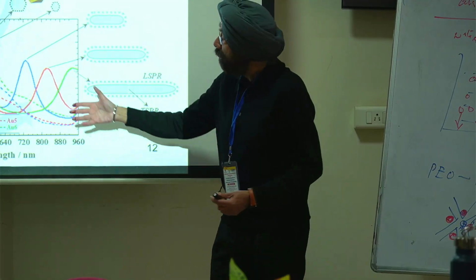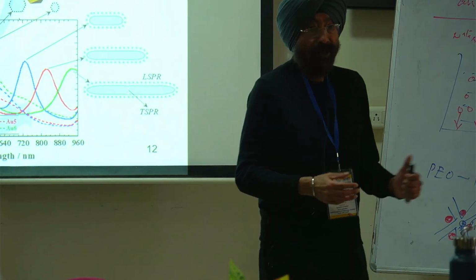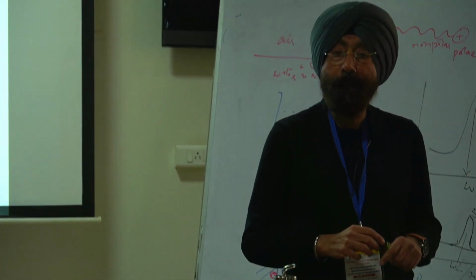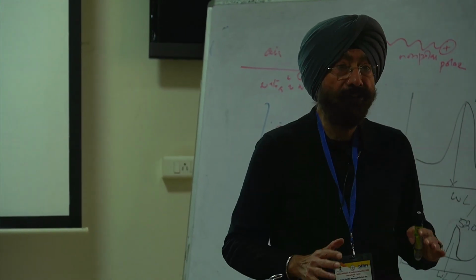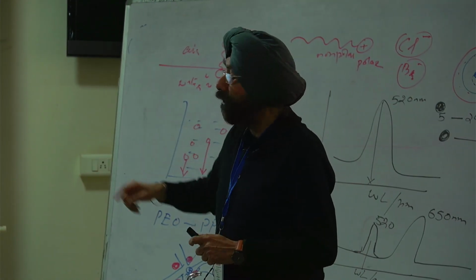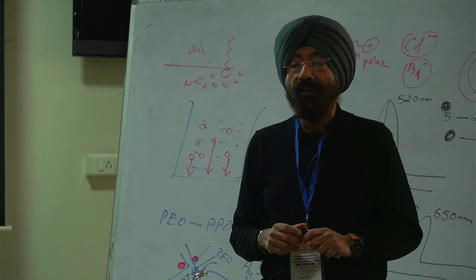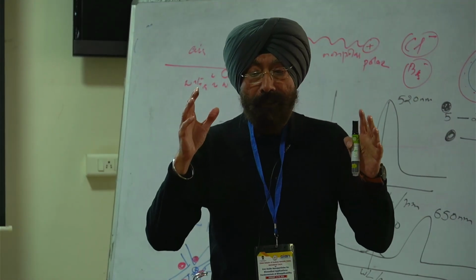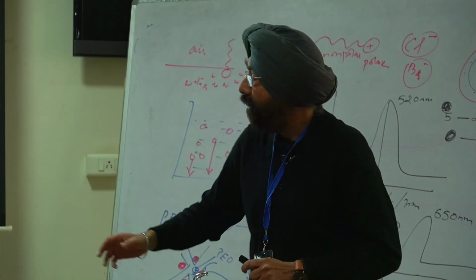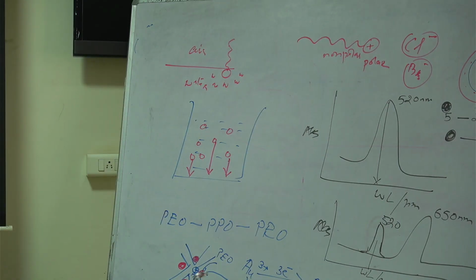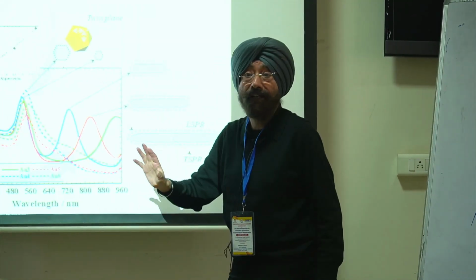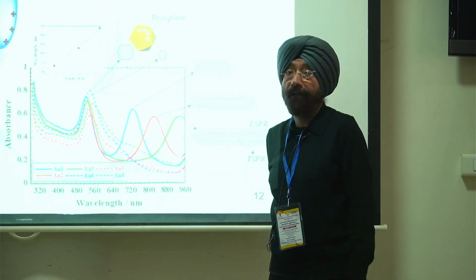So I mean to say, this is the simple way you can test what kind of nanoparticles you have synthesized and what the tentative shape should be. If it is only one kind of shape, you should have only one kind of absorbance. If you have a mixture of different particles, you have different shapes. But this particular peak will only appear if you have rods. If your solution does not contain rods, this peak will not appear, right?